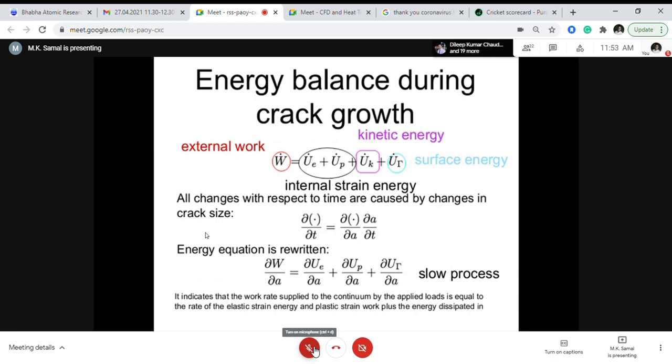You must have studied this theoretically. Suppose there is no defect, and then if we calculate the theoretical strength of the material, this is actually very, very high. But because of defects etc., the strength reduces, and moreover in the presence of a crack, the stresses at the crack tip get elevated.